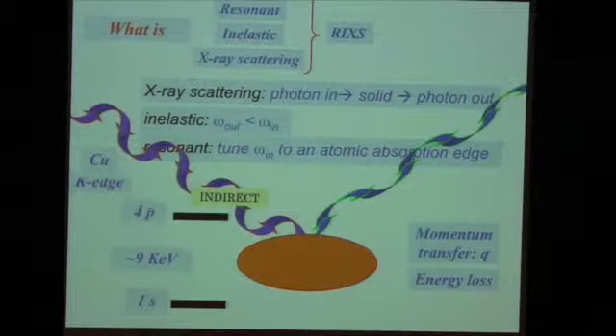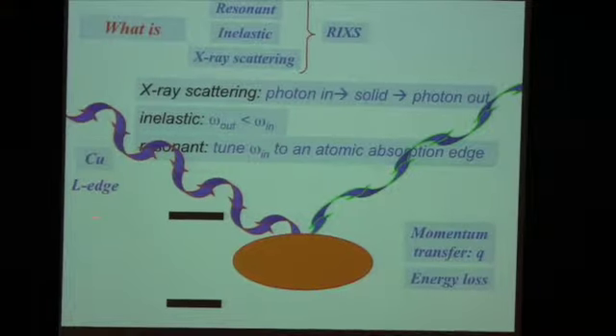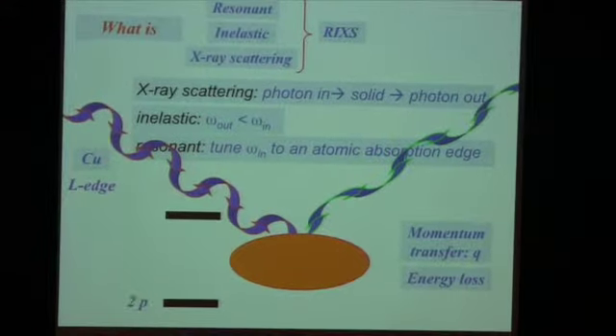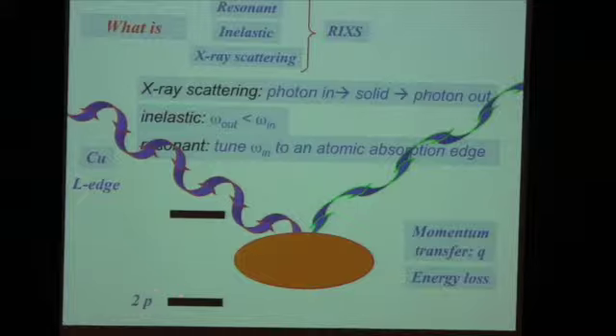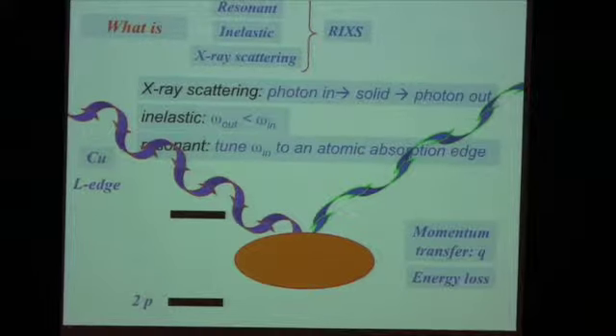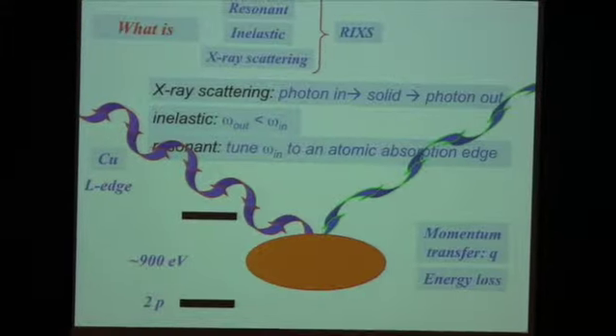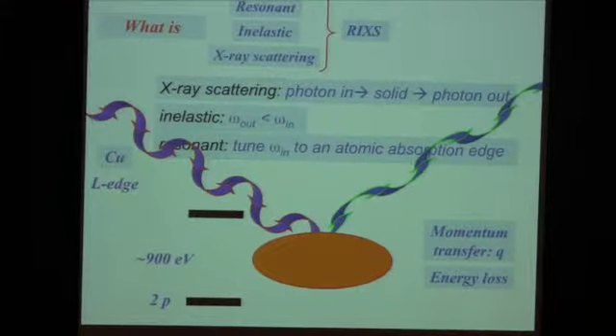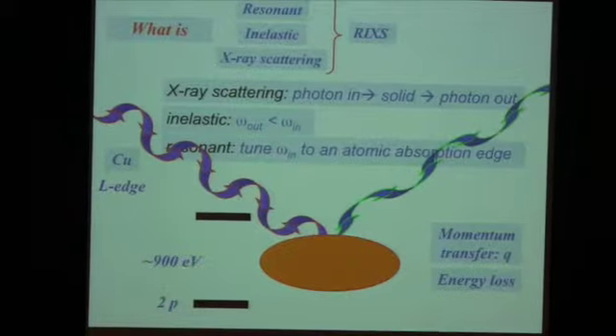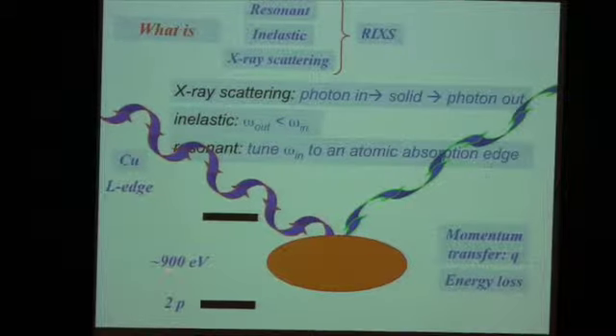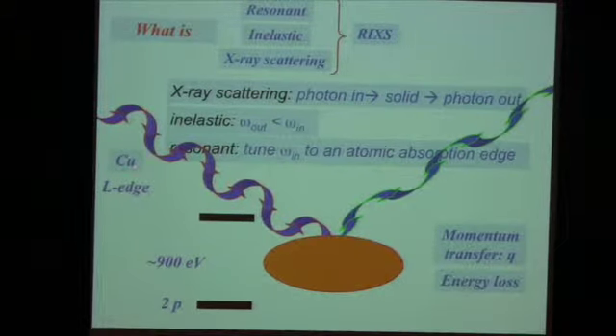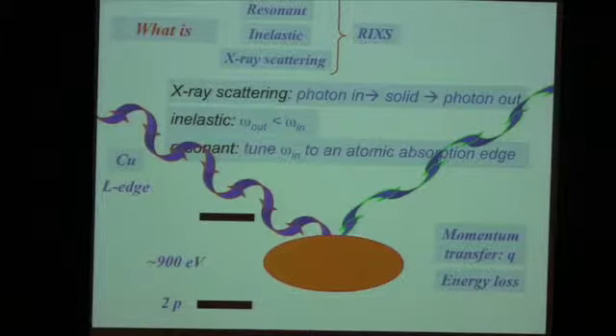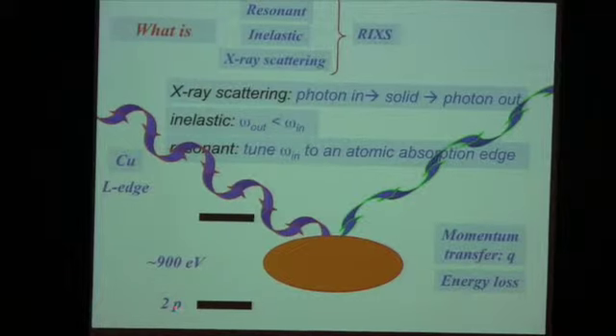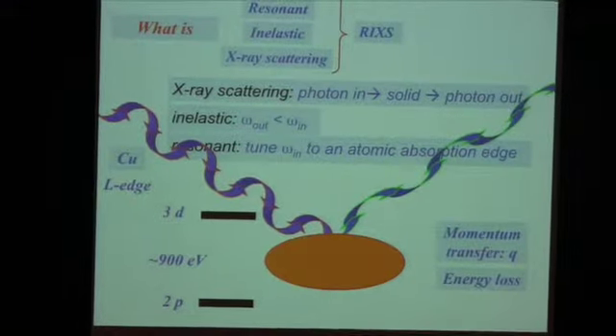You can do this, however, when you switch to the copper L-edge. If you have a copper L-edge, you will not start from a 1s level, instead you start from a 2p core state. This 2p core state is of course at less binding energy. In this case, it's around 1 keV for the copper L-edge. And if you start from the 2p, of course, the dipole transition brings you into the 3d states.